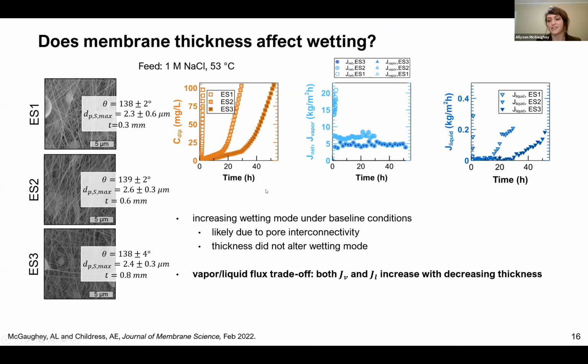Yeah, those are great questions. Thank you for asking that. So the material we used was a blend of PVDF as well as PVDF-HFP, hexafluoropropylene, I think. So it was a relatively hydrophobic material, but yes, we did see these beads, and that was an issue that we didn't end up optimizing for.